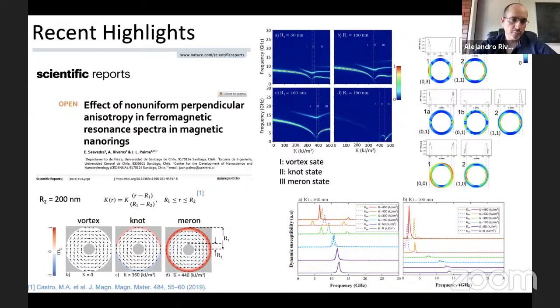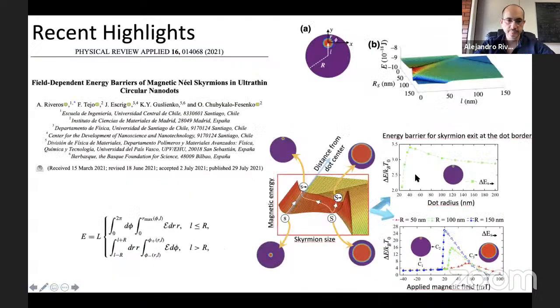In a more recent work, we study the effect of non-uniform perpendicular anisotropy on the dynamic magnetization in nanorings. We choose a radial PMA profile, and here we show the dynamic susceptibility as a function of K and as a function of the frequency of the in-plane pulse. As shown, the frequency modes depend on the K value, and the frequency shift between modes depends on the widening of the ring. We also obtain the spatial distribution for each mode for different K values. Here we show for this particular K value the vortex state, the knot state, and the meron state.